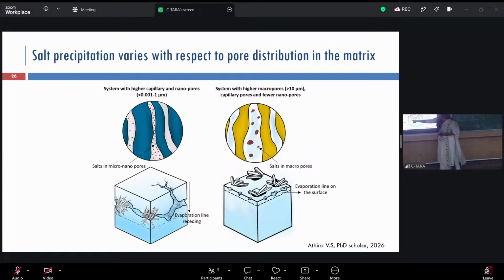But in the other case, you are having small pores. So salt crystals precipitate inside. It doesn't have space to grow or move. It causes cracks in the system. This is your evaporation front and it gets separated into 2 pieces. So you are actually modifying the pore structure of a material to get a better performance.